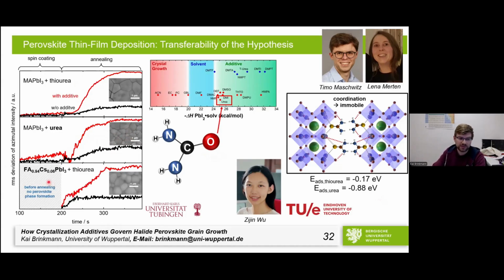And finally, we also tested the same with formamidinium cesium lead iodide. And yeah, basically, of course, we do not have an alpha phase in the beginning. So basically we had to wait for the hot plate, but also there, when we put it on the hot plate, we see one of them orienting, one of them forming large grains the moment when it reaches the hot plate.